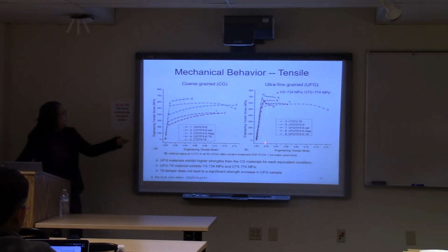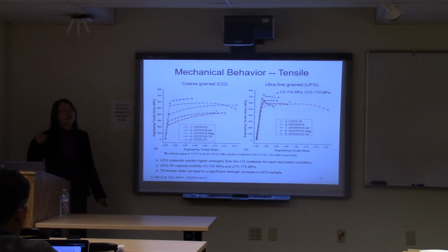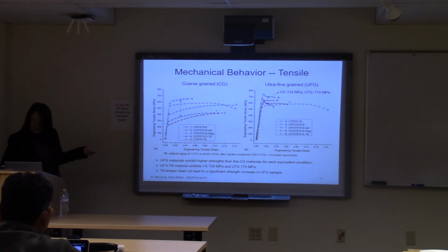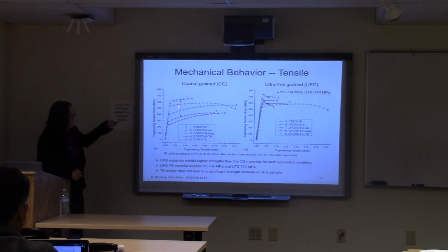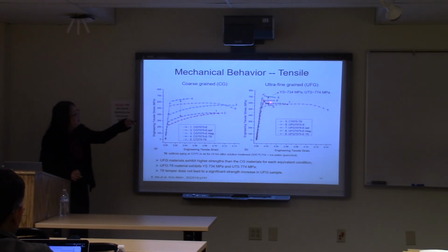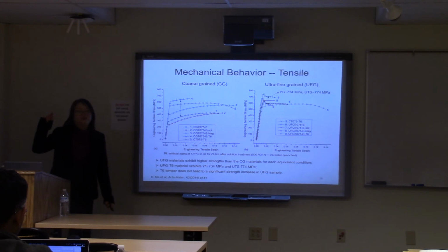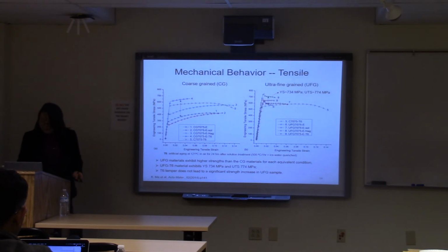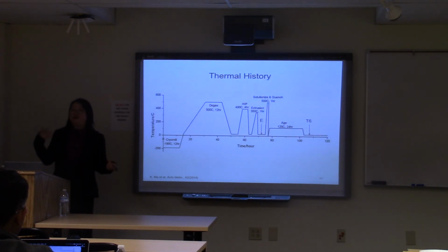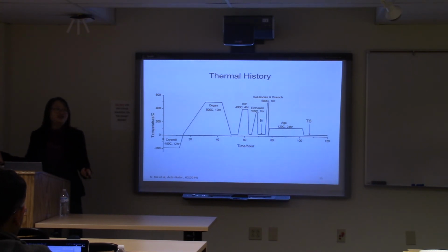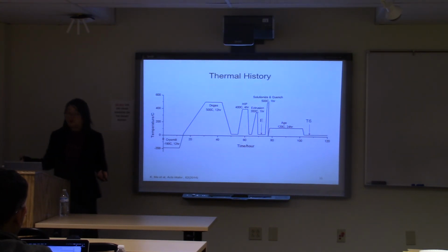So first, the highest strength we can get is 734 megapascals, compared to Curve 5, a commercial 7075 material. This is where I just buy a material from the market and then test it. And more interestingly, I also find that with the T6 temper, the increase from Curve 1 to 4 is much larger than what we can get from the ultrafine grain material. We still get some strength increment from the precipitation behavior after T6, but it's not as large as I want it to be. So now, again, it's time where we need to understand what's going on here. Why didn't I get as much strengthening from precipitation as I see in the traditional material?